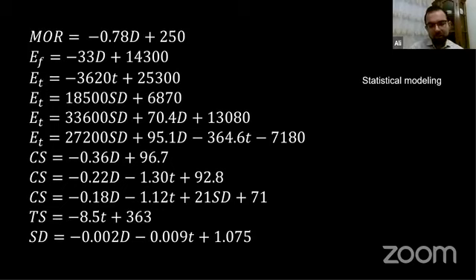So this was very important for us, because when we wanted to order some bamboo, for example, from Indonesia, we didn't have to travel all the way, or we didn't have to necessarily ask them to send us a few samples. So based on more than 5,000 samples, we did some basic formulations on how to estimate, with a good approximation, the mechanical properties like elastic modulus, modulus of rupture, compressive strength, and tensile strength. So we had a very good estimate before we received the bamboo. We could tell the farmers, no, don't cut that bamboo, we want this property, so please cut the bamboo with this specification.